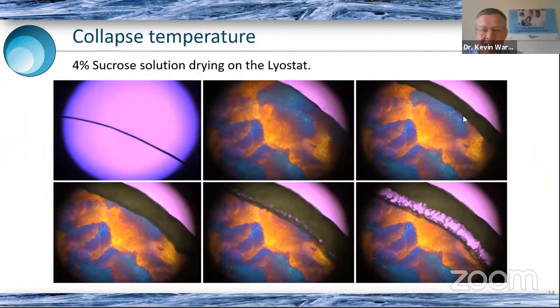has been created. Here we're at about -40 degrees, so we're below the collapse temperature of sucrose, so everything looks fine. And I'm going to jump to the picture at the bottom middle, and you can see that after having raised the temperature, behind the drying front, so between the frozen material and the dried material, we've now induced collapse. And what we can do is pinpoint the temperature at which the first defect started by rewinding through our gallery of images. And now, if we go to the picture on the bottom left, you might just be able to make out the